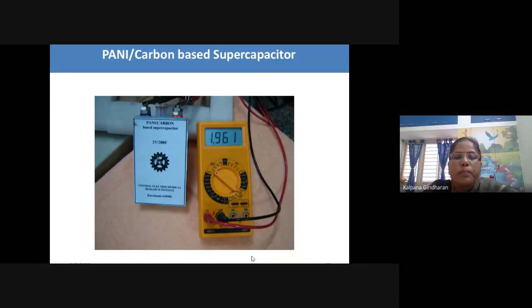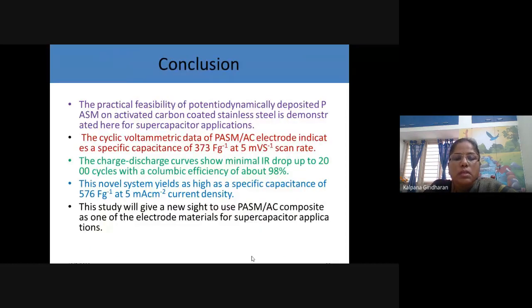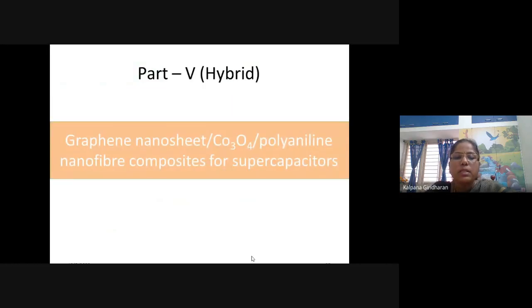So we made a capacitor out of it with the polyaniline activated carbon based supercapacitor, which was giving 1.96 volts. This is the conclusion. So the last part is graphene nanosheet with cobalt oxide polyaniline.